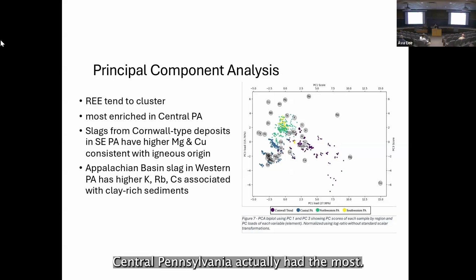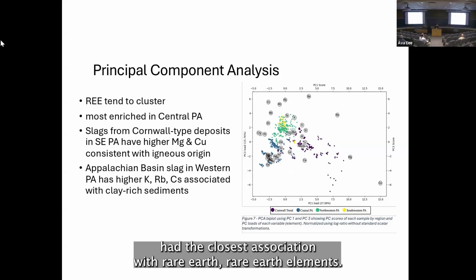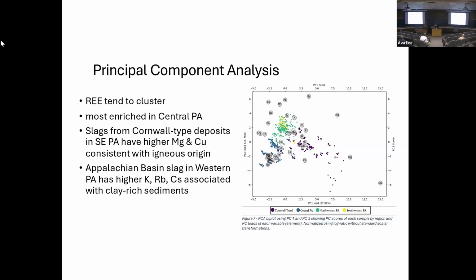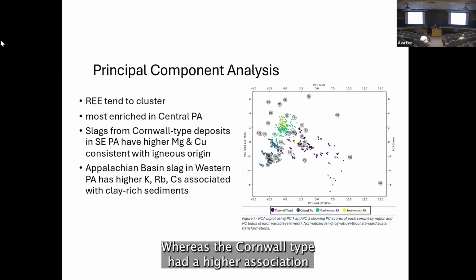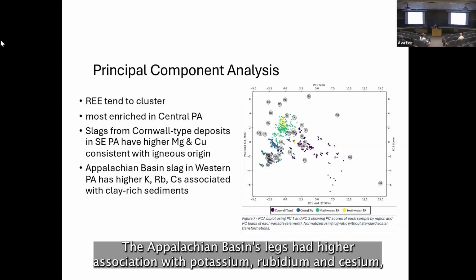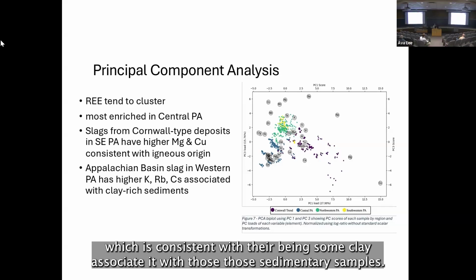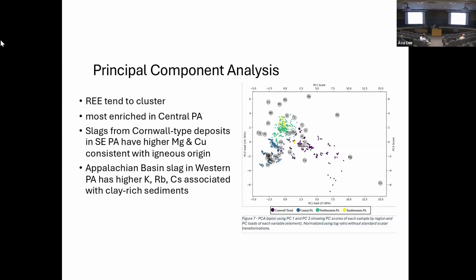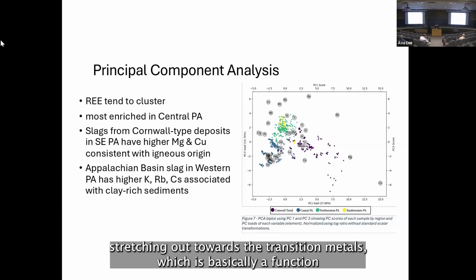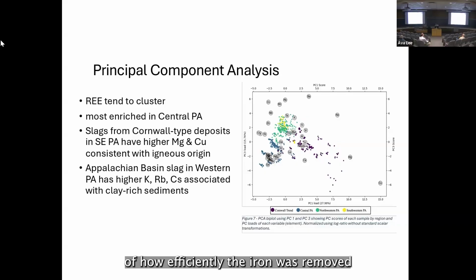Central Pennsylvania, those are the blue dots on there, actually had the closest association with rare earth elements. Whereas the Cornwall type had a higher association with magnesium and copper compared to other samples. And the Appalachian Basin slags had a higher association with potassium, rubidium, and cesium, which is consistent with there being some clay associated with those sedimentary samples. And all of them show some stretching out towards the transition metals, which is basically a function of how efficiently the iron was removed from the slag samples.